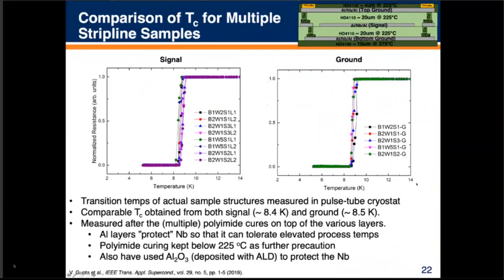So one thing to check out is the transition temperature of the signal trace, as well as the ground traces after we do all of that processing on the thin film. And so here you can see from multiple batches, we're looking at transition temperatures around 8.5, 8.6 or so for the signal, and similar for the ground. So this gave us confidence that we're leaving sufficient superconducting properties for the niobium that it could still be used as a superconducting strip line. Again, that aluminum protects that layer. We also cure the polyimide at 225 C or below. And as I mentioned, we've also looked at aluminum oxide deposited with ALD to protect that niobium. In that case, we can actually drive it to even higher cure temperatures.